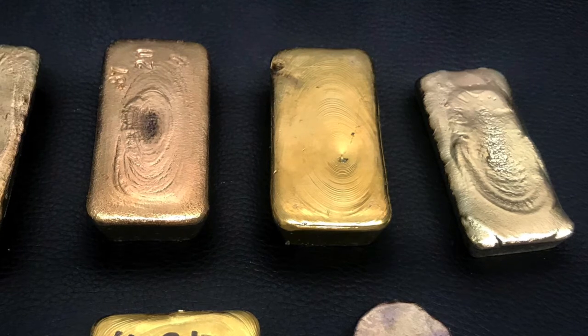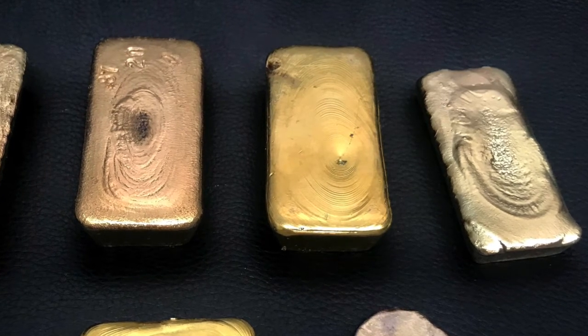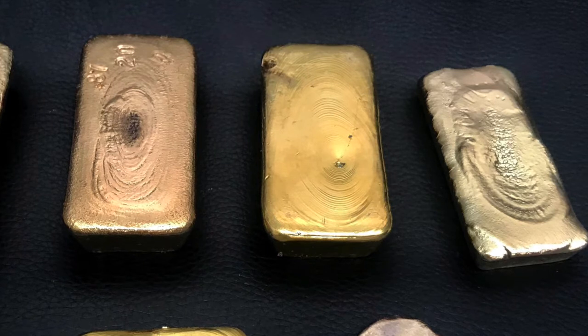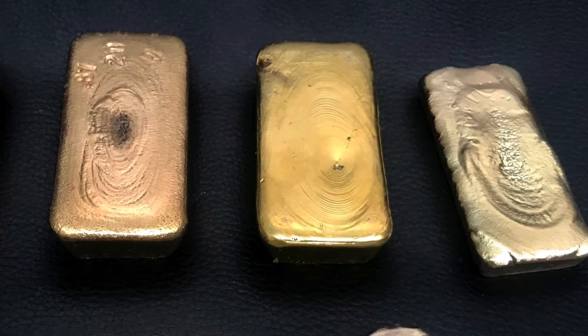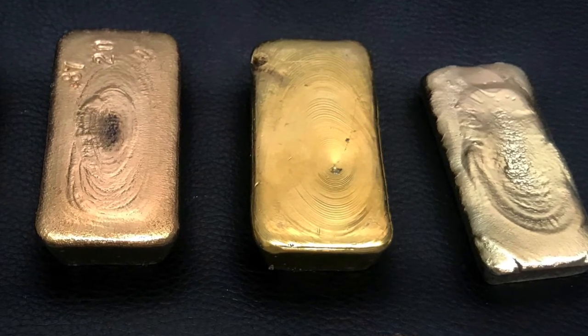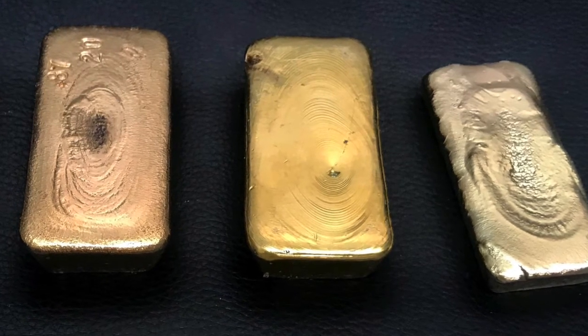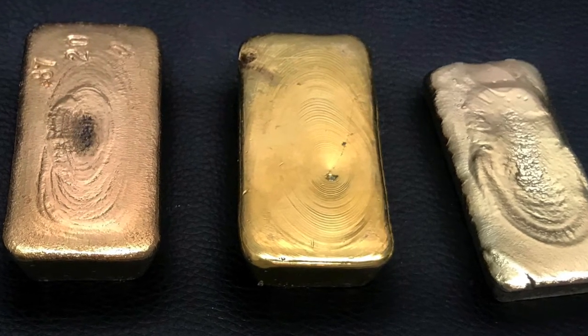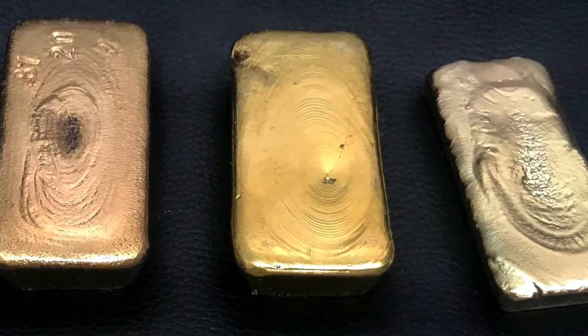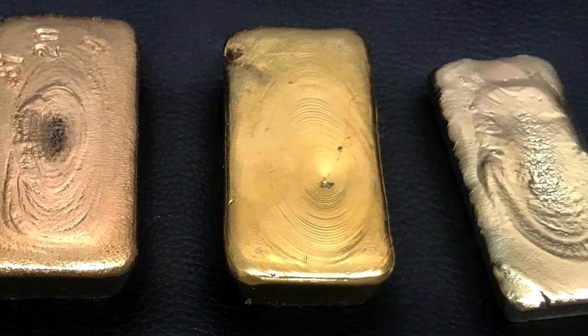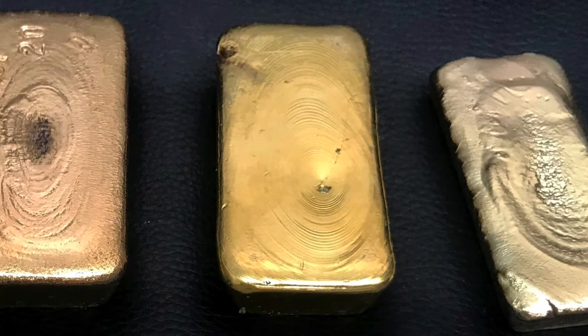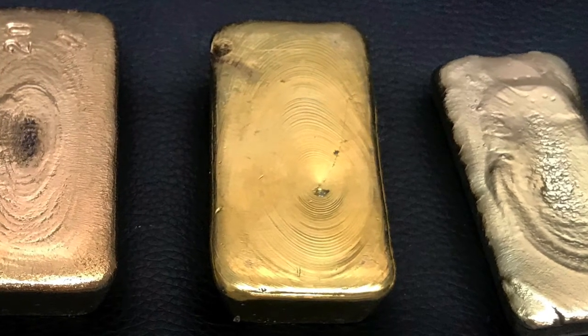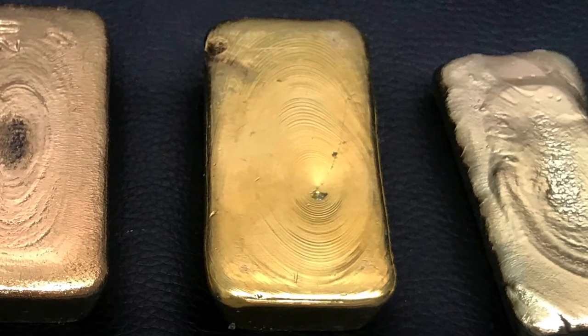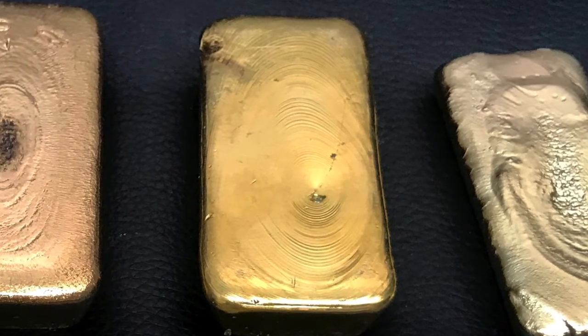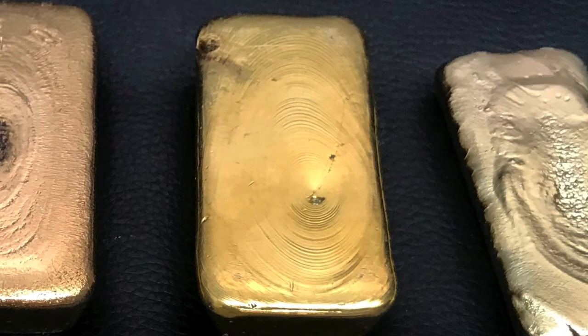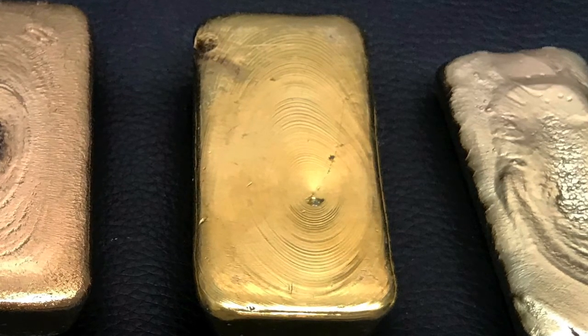Bringing it up into the mid to high 90s does, however, assure that you're getting a good, accurate analysis of the gold that you're selling to them. So the nitric acid leach is worth the effort on that score. Some of these are less pure than the others because we were still working out the nitric acid leach for the quantity of gold that we were doing. And by the time we got to the 21 ounce bar there, we had it down pat.